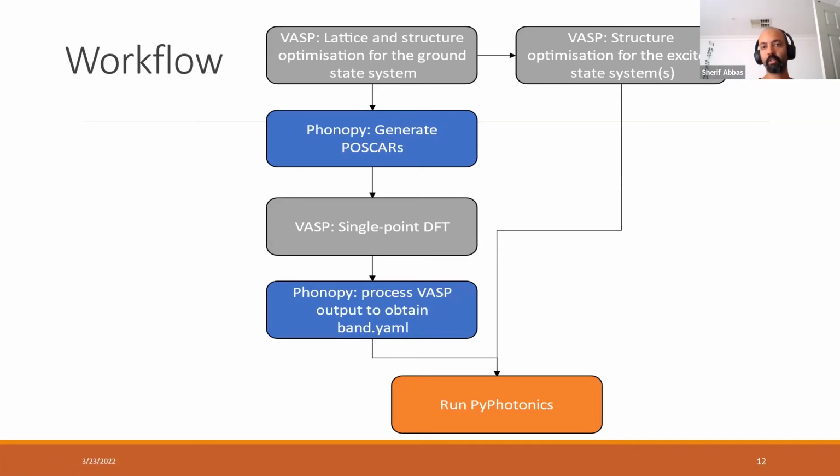While running your CDFT to optimize the excited state, you can actually start doing the phonon calculations. We don't need to do phonon calculations for the excited state. We just need to do phonon calculations for the ground state in most cases. So we take the ground state geometry, we do the phonon calculations. Now, how do we do the phonon calculations?